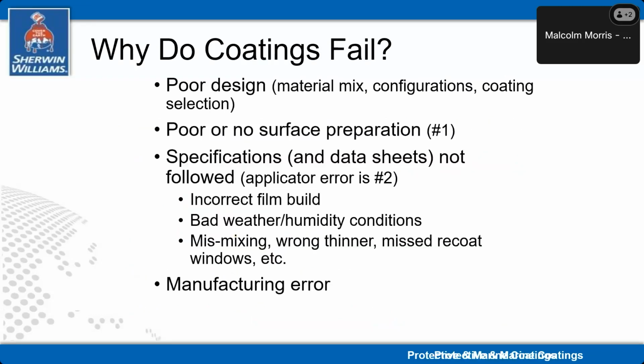Why do coatings fail? It could be poor design. You know, if you've got a structure with water traps built in there, poor materials, if you've got different metals forming a bimetallic corrosion reaction, poor coating selection, you know, not selecting the right materials for the actual situation. Surface preparation, say that again, can't stress that too much, that the vast majority of coatings failures are down to inadequate surface preparation.